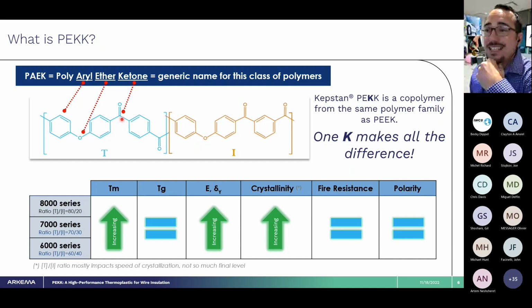And in the case of PEKK, what we're saying essentially is poly-ether-ketone-ketone. So you have an ether linkage between your aryl ring and then two ketones. Now, in the case of PEKK, this is going to give you, by having two ketones and one ether, a higher glass transition temperature, higher strength, and a higher melt temperature.